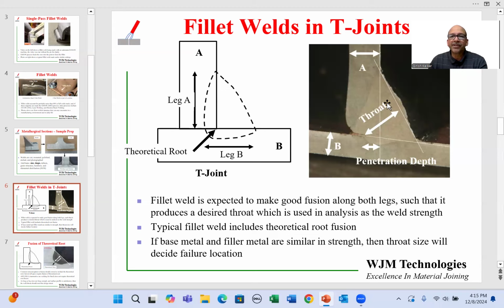Oftentimes, the material that you add for welding is quite similar to the material that we are welding to. So A and B and the filler wire will be a close match, not exactly. And again, there's a separate video on that as well. Let's say that's a close match. In this case, we will notice that A is fairly narrow, B is narrow, but the throat is actually much wider. What that means is the weld will in all likelihood be much stronger than components A and B. So if you take this weld and try to bend it out of shape, it is quite likely that components A and B will bend before the weld comes apart.